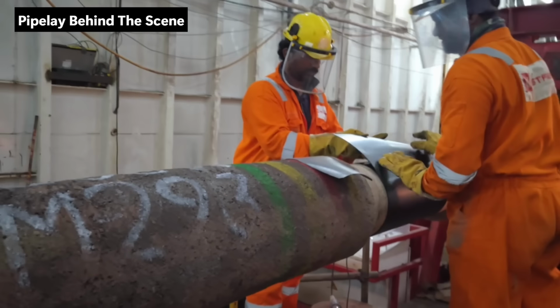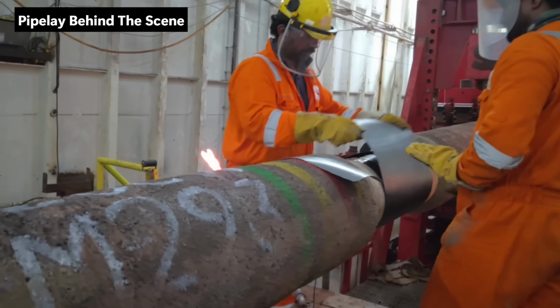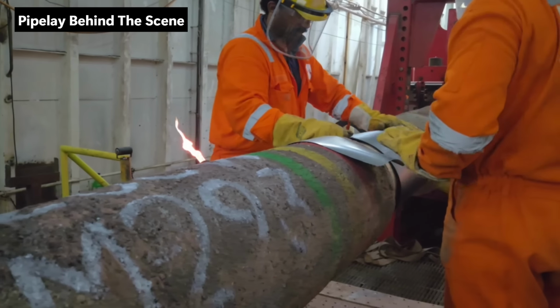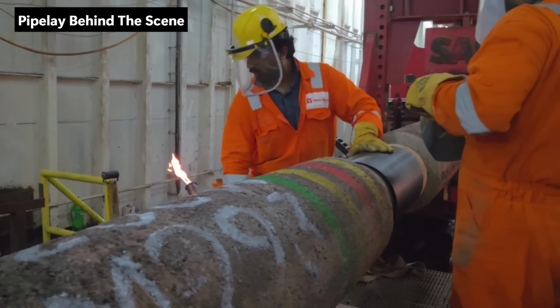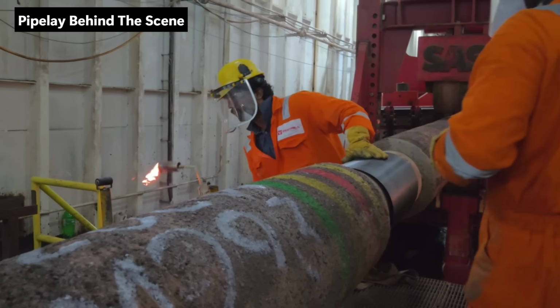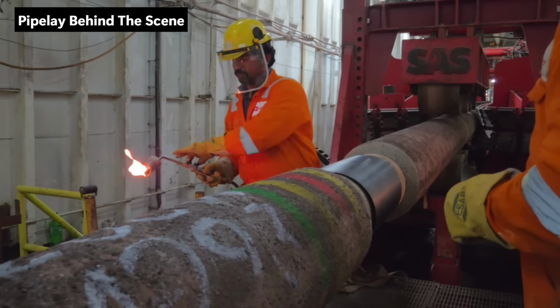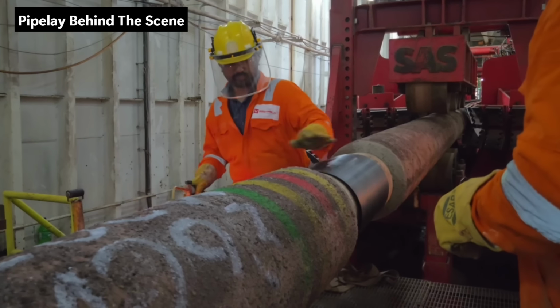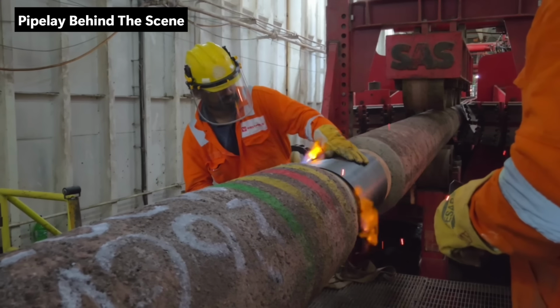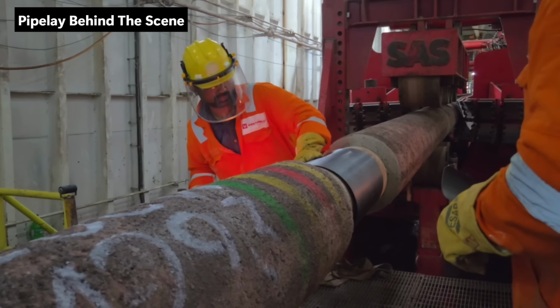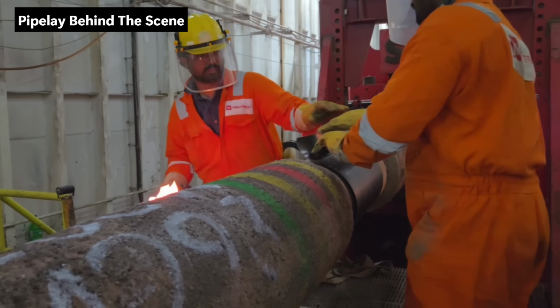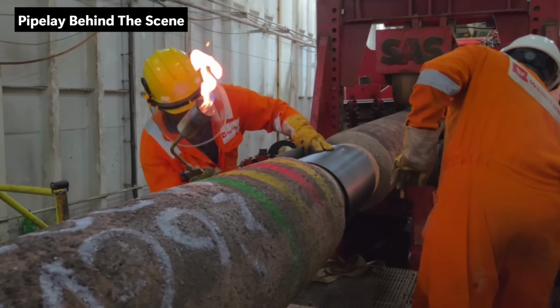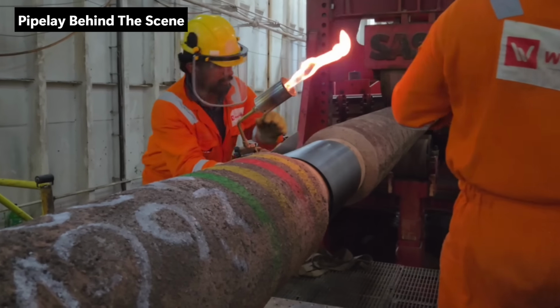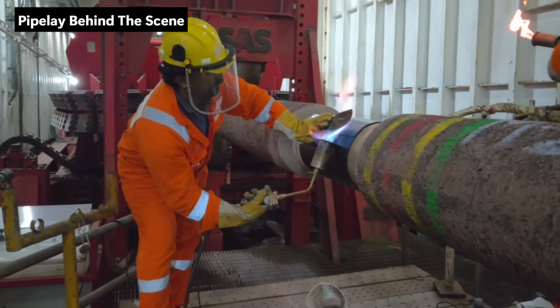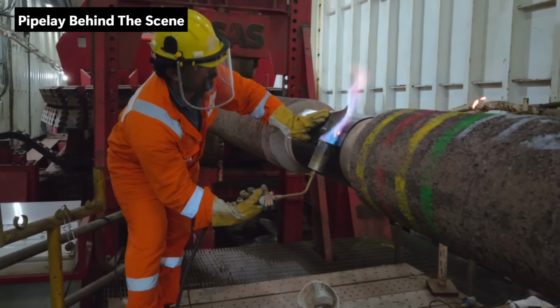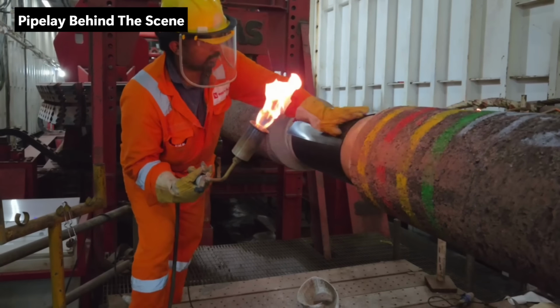The sleeve is wrapped around the pipe over the weld area. Heat is then applied evenly around the full circumference. As it heats up, the sleeve shrinks and conforms tightly to the pipe surface. The adhesive melts and bonds. The sleeve becomes part of the continuous coating system. That sleeve is what stands between the weld and the seawater for the life of the pipeline.